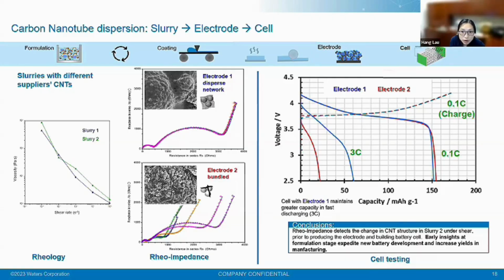With those conductive networks, you can see a huge difference in capacity loss, where the one electrode drops off much faster compared to the one that has a much better conductive network. So this is giving you an idea when you're looking at slurry characterization. This is giving you information before you lock in coating and drying together that maybe you don't have a good product, so you need to rerun the sample compared to previously. So it gives you some insight into the formulation and also potentially provides better yield for your production as well.